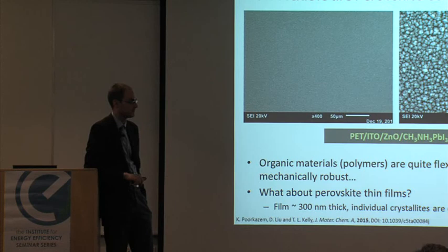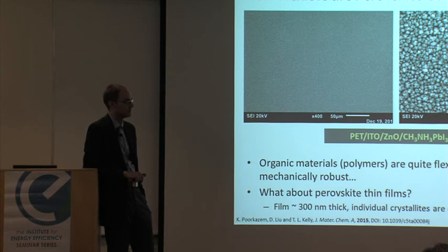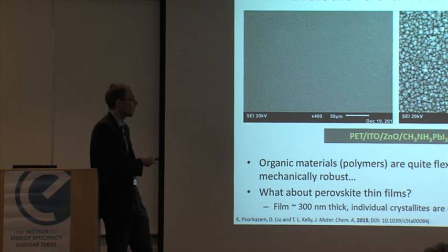So I would expect that for the thicker film, you should be able to make a very thick film because you don't limit by the mobility by extraction. But what you show is that with thicker film, you also have the issue with extraction. And I would assume that for that case, the main drop in the PCE is due to the lower fill factor and also lower short circuit current. So I think it comes back to morphology.